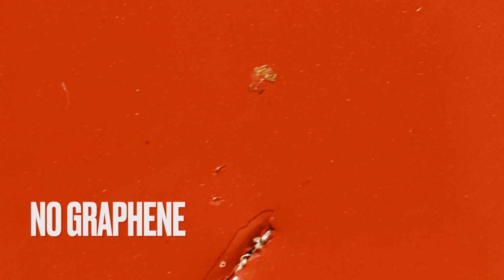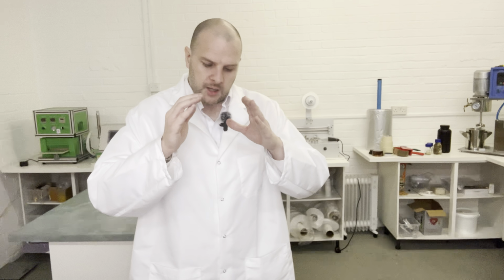We compare that to now the puncture tests. The puncture tests, we took a chisel, approximately about 1/2 meter. We dropped the chisel and it made an impact into the panel itself. The difference was that the one that did not contain graphene flaked off, and actually the puncture wound and the paint damage was a lot more than the one that had graphene in. So the one that contained graphene, we see a very, very straight, accurate puncture wound, and there's no flaking of the paint whatsoever, which in my opinion is amazing.